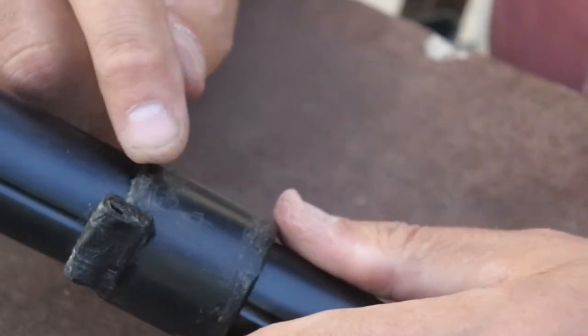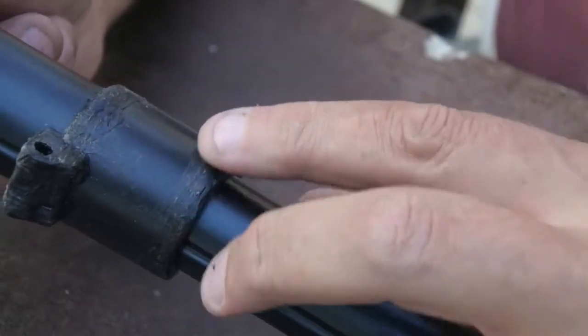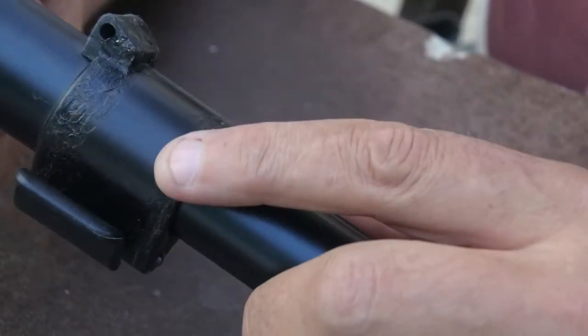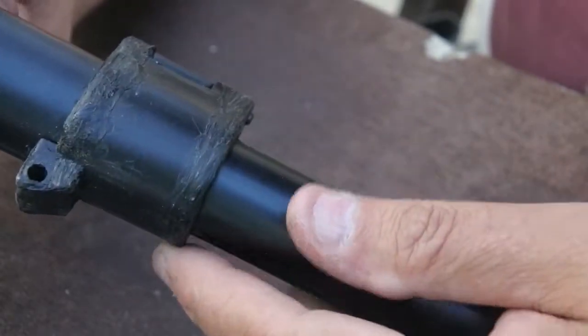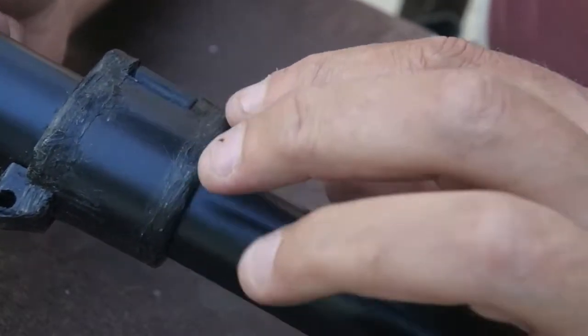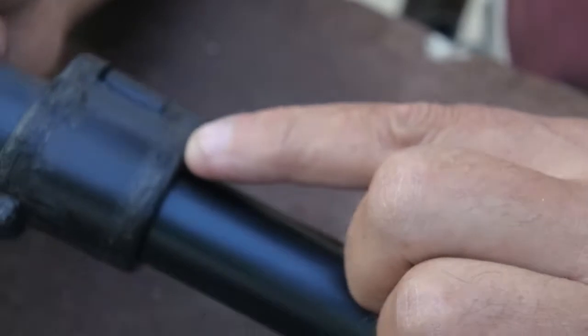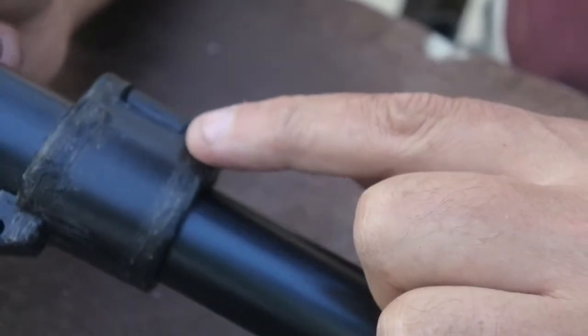When you wind this glass fiber, make sure to wind it so it overlaps quite a bit. On the overlapping area, I needed to add more material because the material from below wouldn't flow through both layers of fiberglass.